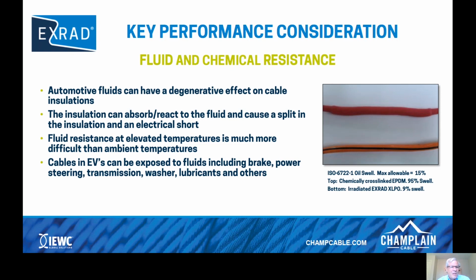That can result in disastrous situations where the insulation might even split on itself or be split easily when moved around. Fluid resistance at elevated temperature is much more difficult than at ambient temperatures, and it should be noted that for every 10 degrees you go up, the swell or weakness of the insulation is going to double. If you had something that was swelling 10% at 50 degrees, it's very likely it would swell to 20% at 60 degrees. Take a look at the picture on the right. Again, we have a rubber type cable, and that's swelled 96%.